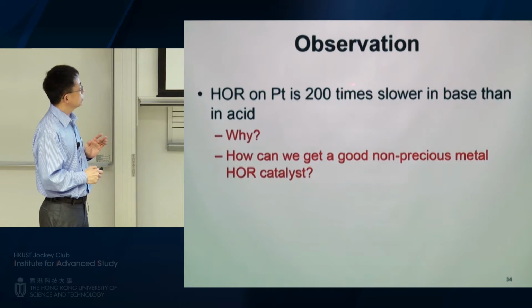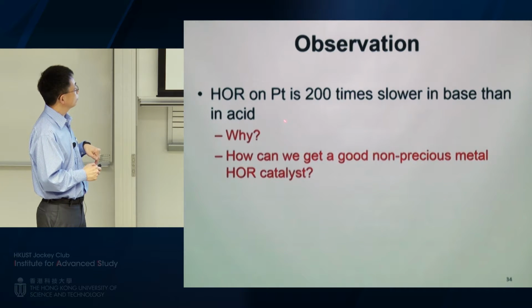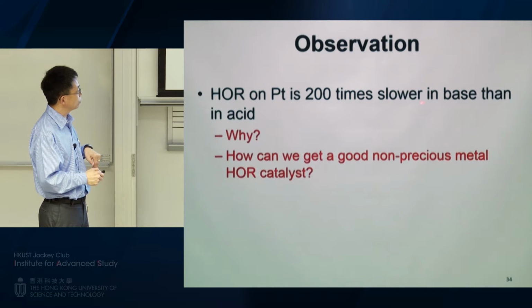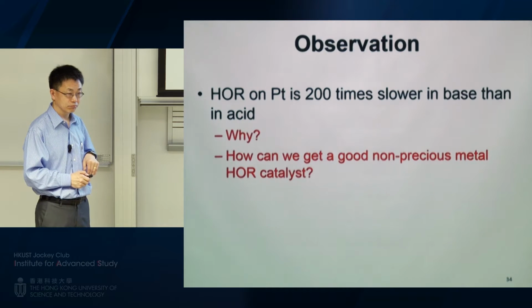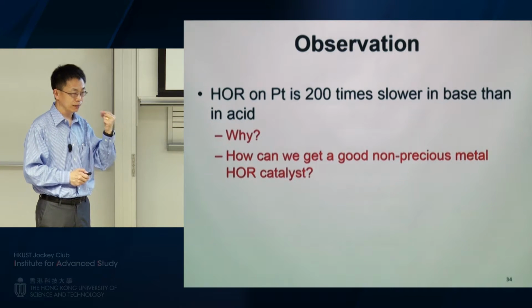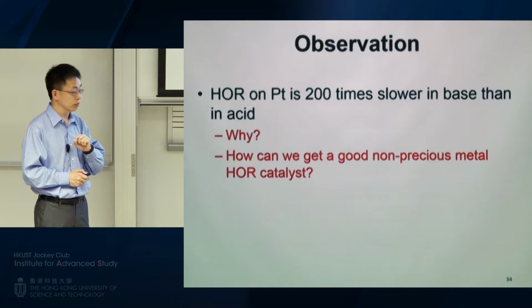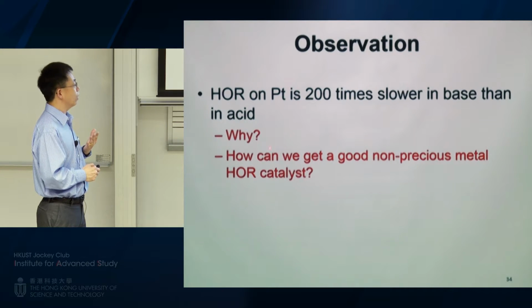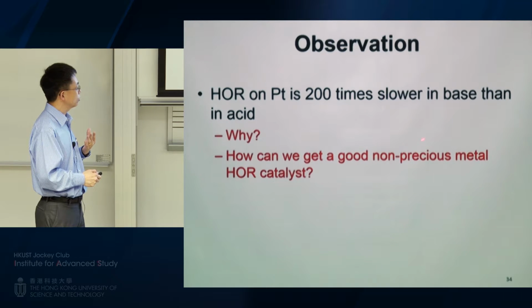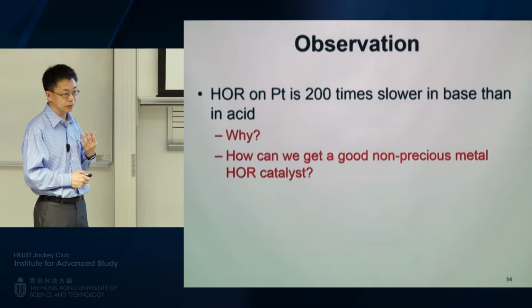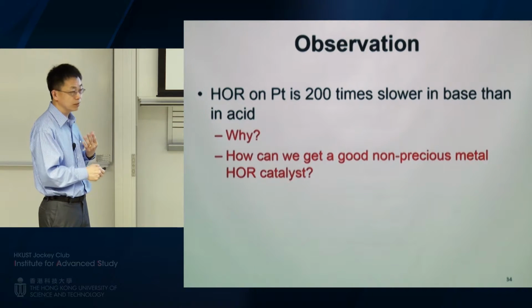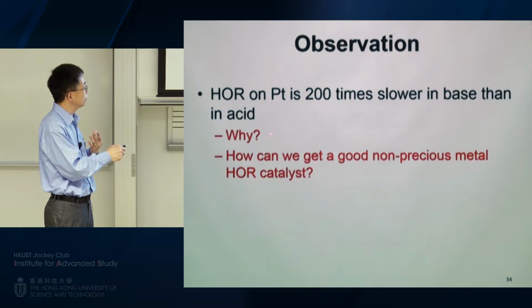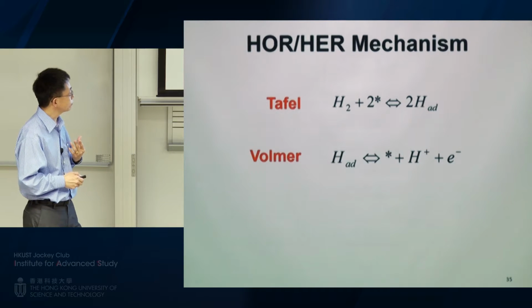Let me just simply say there's literature data out there. HOR on platinum is about 200 times slower in base than in acid. So this is very intriguing. Somehow, when you switch from acid to base, it becomes slower. So the question is why? And how can we get a good non-precious metal HOR catalyst? Because this is where we're going, right? But we need to understand why here. And hopefully, by knowing that, we can get the catalyst we want.